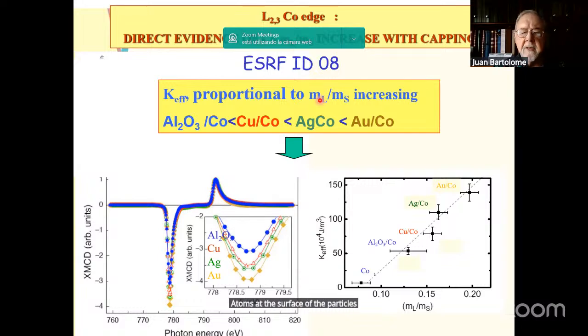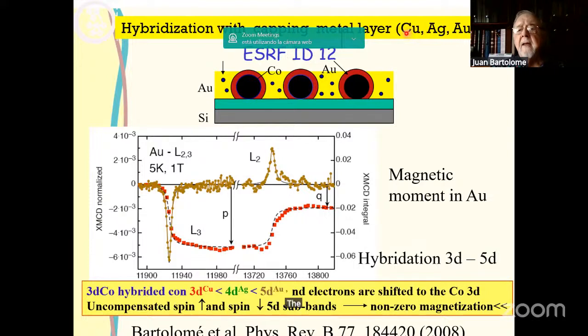To understand better what was happening at this surface, we then studied the XMCD at the capping metals, the different elements. So here I show you the results for the gold capping. So we have gold around the central cobalt particle. And when we measured as a function of field, at 1 Tesla and 5 Kelvin, we did clearly observe an XMCD signal at the gold L2 and L3 edges. So this means that we have magnetic moment in gold.